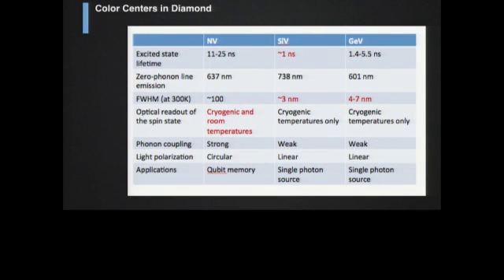So if you want to talk about deep color centers, you have the NV center, the silicon vacancy center, and the germanium vacancy center. Here's just some data that we've been able to accumulate, where the zero phonon line is for the NV center, well known, for silicon and for germanium. Full width at half max: if you notice, the NV center is very broad. However, the silicon and germanium are very, very sharp. The phonon coupling is very strong in the case of the NV center, very, very weak in the case of silicon and germanium.